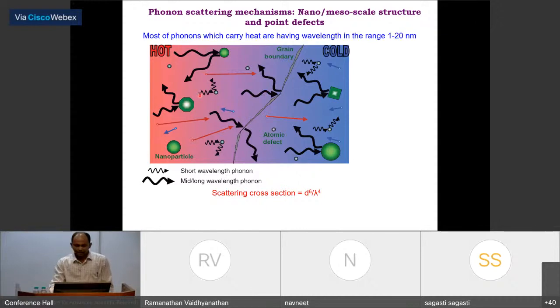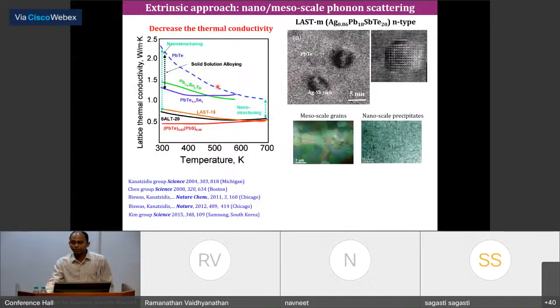And in this direction, several important papers came in, not only in lead telluride, also in bismuth telluride. Here I'm showing a lattice thermal conductivity versus temperature plot. For the champion material lead telluride, you can see the thermal conductivity can be decreased when you have a solid solution. This is known from the 1950s and 60s.